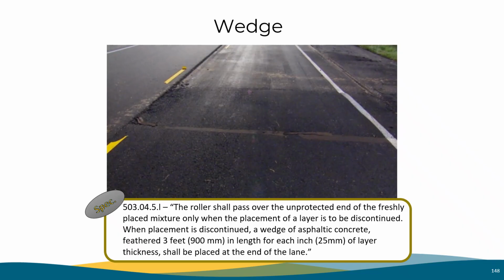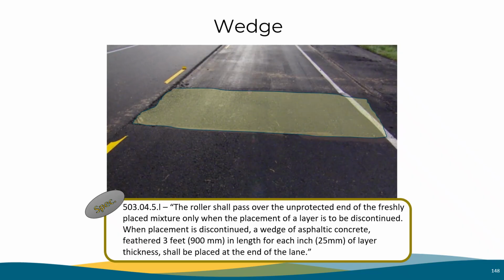At the end of each day's paving, we must place a wedge to smooth out temporary transition, as written in the standard specifications. The roller shall pass over the unprotected end of the freshly placed mixture only when the placement of the layer is to be discontinued. When placement is discontinued, a wedge of asphaltic concrete, feathered 3 feet in length for each inch of layer thickness, shall be placed at the end of each lane.